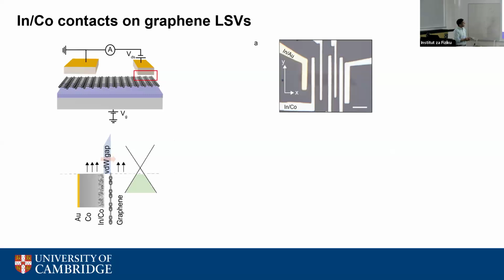So what we thought is we can use these van der Waals contacts on graphene, where we have this vacuum gap between the metal and the semiconductor, which is the van der Waals gap. We want to use this van der Waals gap as a barrier to introduce the spin. And we don't use any tunnel barrier, because tunnel barriers are really hard to grow on graphene, since graphene is really flat. So we make these lateral spin valves in our lab. We just use mechanically exfoliated samples because these samples are of good quality.